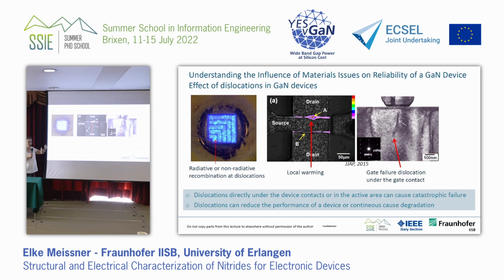Now when everything comes together, what we learned about growth, epitaxy, properties of substrate, properties of dislocations, now we put everything together and say, okay, how does it look in a device? And it's getting more complicated, but we can see quite a lot of things. Here you see a visual picture of the photoluminescence efficiency, for example, of a LED, and you see that there are places of non-radiative recombination at dislocations. So you see that, actually it's vice versa. So you see that there are places that shine, so it's illuminated. Actually, it's not that this is shining more than this one. It's color-coded in the wrong way.